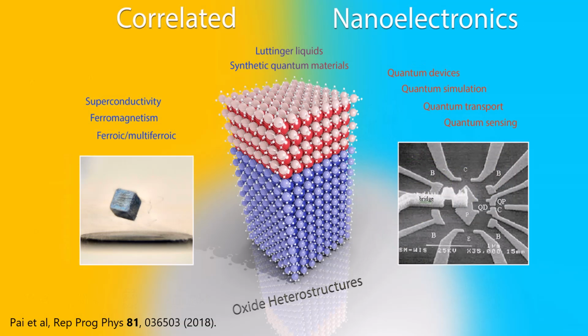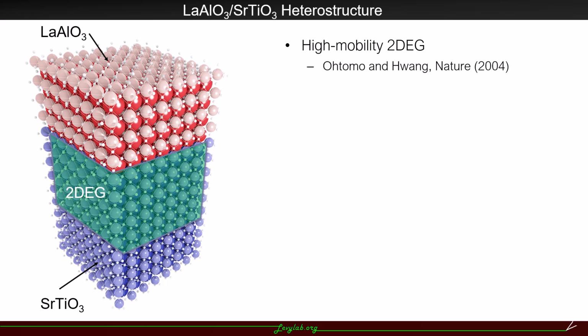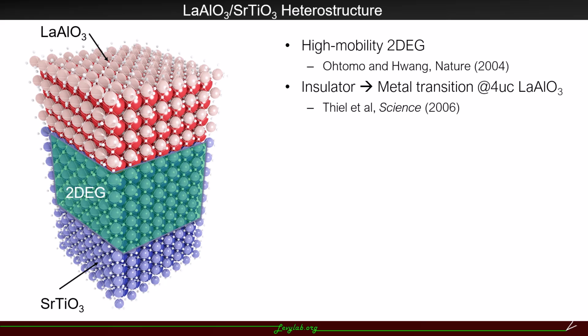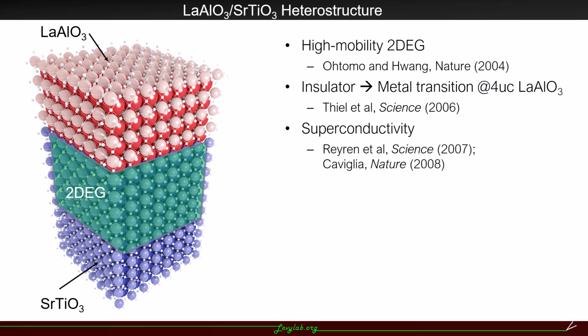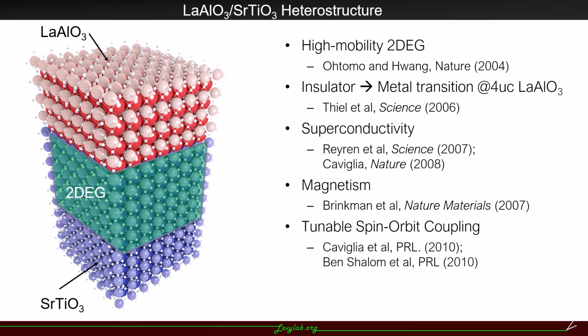We are interested in lanthanum aluminate strontium titanate heterostructure. It has been shown in 2004 that there is a high mobility electron liquid at the interface. When the lanthanum aluminate layers are 4-unit cell, we can tune the interface through an insulator to metal transition. The system has also found superconductivity, magnetism, and tunable spin-orbit coupling. In this talk, we're interested in superconductivity.